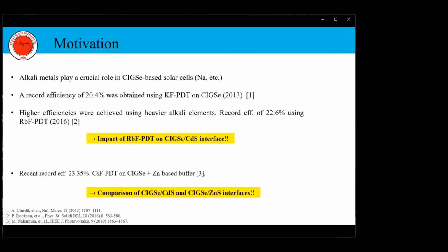A recent record efficiency of more than 23% has been obtained by the application of cesium fluoride post-deposition treatment on the CIGS absorber and using an alternative zinc-based buffer layer. Therefore, in this work, we aim to also compare CIGS/cadmium sulfide and CIGS/zinc oxysulfide interfaces.